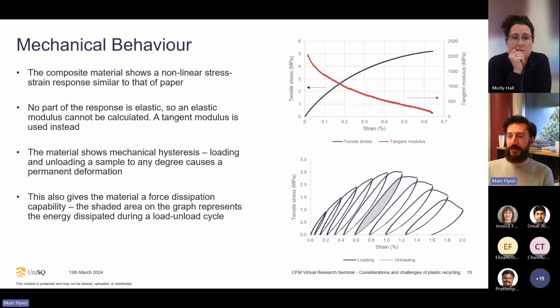When we're looking at the mechanical behavior, we get this non-linear stress strain response. So there's no elastic part of the curve. It's constantly curved, and the apparent elastic modulus is constantly changing. So what I've measured here is the tangent modulus, and we can see it starts off at about 2000 megapascals, and then as you extend the material more, it gets less stiff, and at its breaking point, it's all the way down at about 200 megapascals.